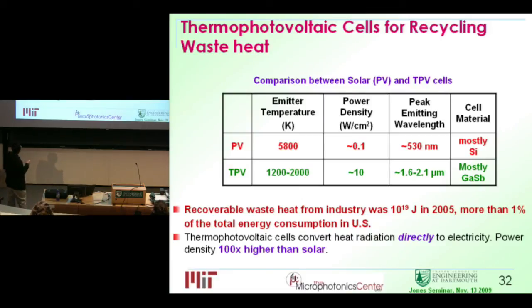In thermal photovoltaics, we are looking at furnaces we burn on the earth, in the factories, in the steel works. And that temperature is typically between 1,000 Kelvin and 2,000 Kelvin. Because your temperature is much less, your emission wavelength is much longer. That's in the near infrared regime. So you need a material other than silicon to absorb it. And currently we're using gallium antimonide, which has the adequate band gap. One thing to notice is actually the power density is much higher than solar.